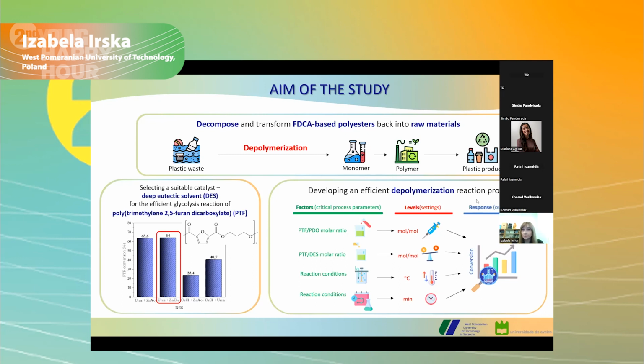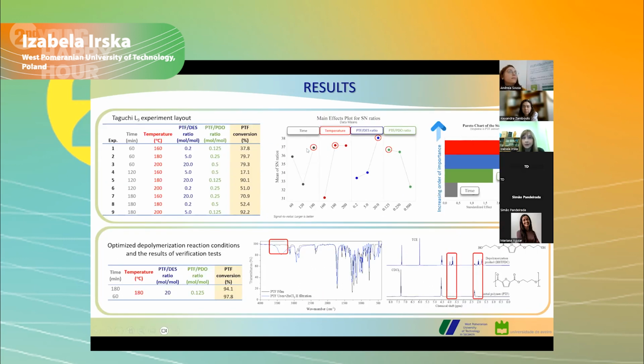The research presented here addresses only the first step of the chemical recycling process, which is the depolymerization reaction. The optimum reaction time is 3 hours at 180 degrees, with the lowest amount of DES and the highest amount of PDO. What is more, temperature can be considered the most significant factor affecting the depolymerization reaction of this polymer, whilst the reaction time is the least influential one. In the final step, the proposed optimum conditions were verified experimentally, yielding a conversion exceeding 94%.